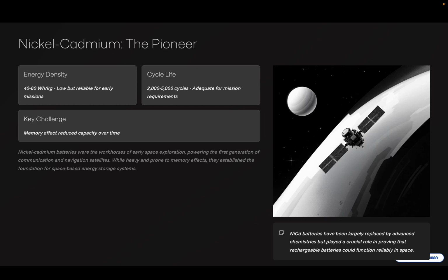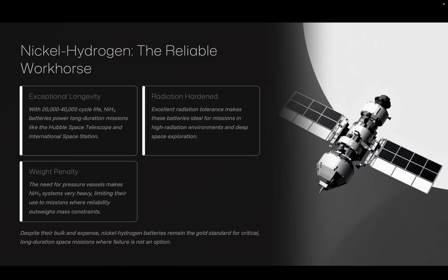Now, if you see the different types of batteries used in the satellites, earlier we had nickel cadmium batteries. The cycle life of the nickel cadmium batteries is 2000 to 5000 cycles. And we can see that the memory effect is present in the nickel cadmium batteries, which is relatively lesser in other batteries. And if you see the nickel hydrogen batteries, the cycle life is 20,000 to 40,000 cycles, and these are better than the nickel cadmium batteries.